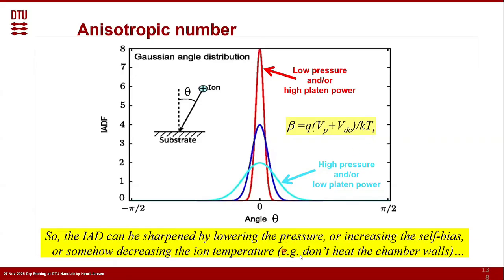And there will be a moment, of course, when you cannot go further, because you have to take into account that at lower pressure, because of the high bias, the directionality is better, but also your mask is under higher bombardment. So it could be that your selectivity is going down. So you have to be willing to live with compromises. I just skipped this one because of time, but you can see a little bit later on if you want to check.